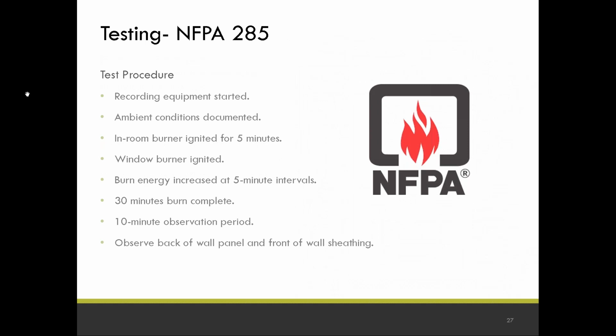So the procedure is you start recording, you record your ambient conditions, you turn the in-room burner on for 5 minutes, you ignite the window burner, then 5 minutes later, you increase the energy at 5-minute intervals. At 30 minutes, the burners are turned off. At 10 minutes, you watch it on the wall, and then you take it all down, look at the back of the panel and the front of the sheathing.